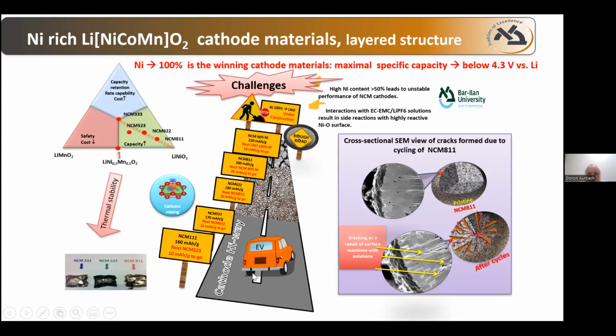And as we go on this road, we go up with the concentration of nickel. So NCM 111 means 33.3 percent nickel. We go to 523, which means 50%, 622 means 60%, 811 means 80%. We can go to 90% and finally to 100% nickel with LNO. And the energy density increases and increases. The specific capacity increases and increases.